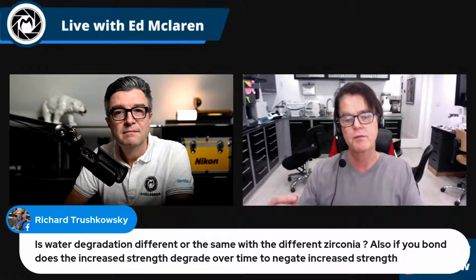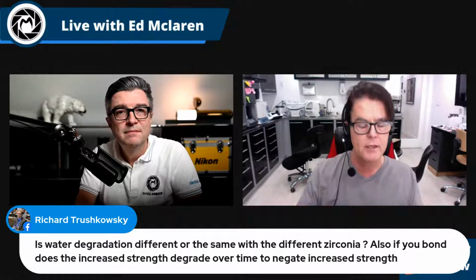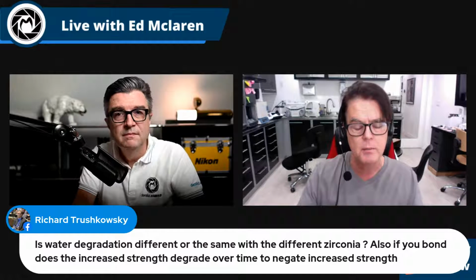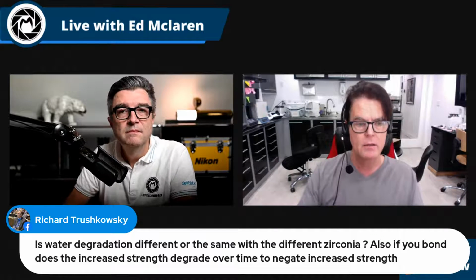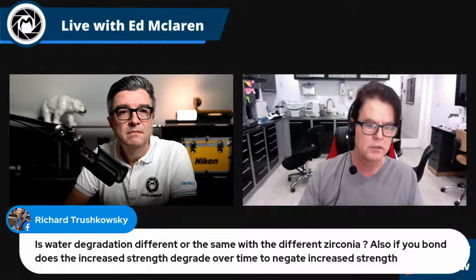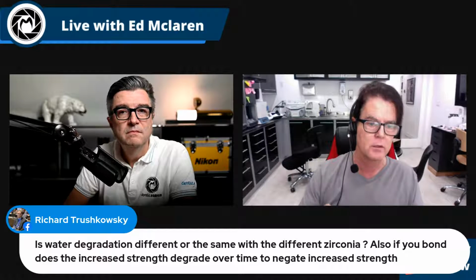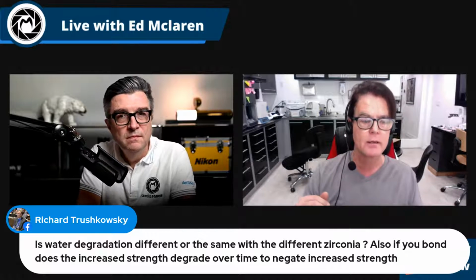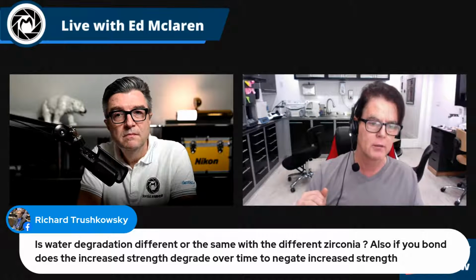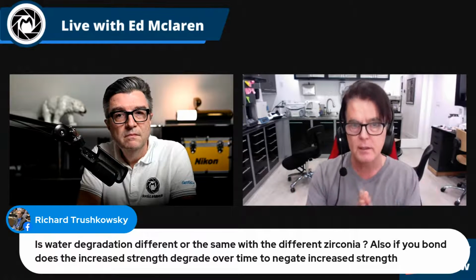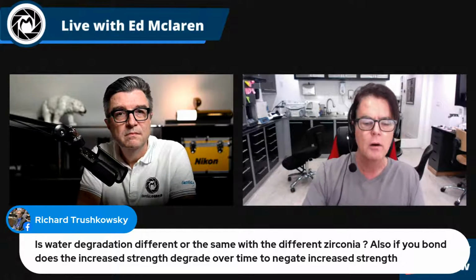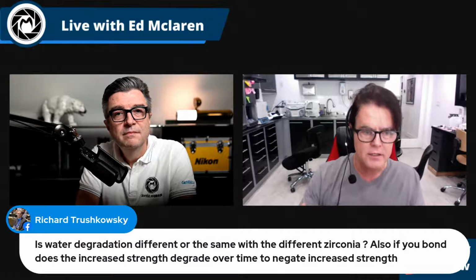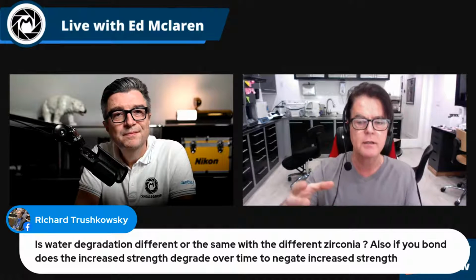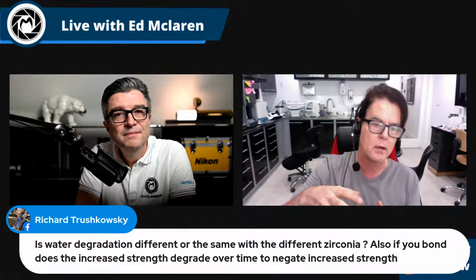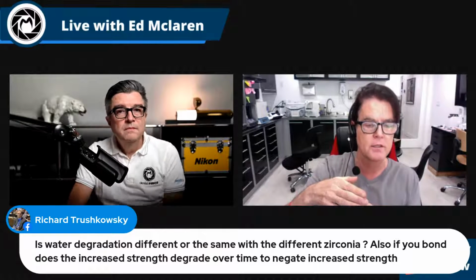All right, so let's fast forward to dentistry. When the FDA, and I don't know about the governing bodies in Europe, made the companies put in alumina, somewhere between a quarter to 0.5% of alumina. If you add that, you don't get hardly any low temperature degradation, at least with normal firing, at least now we know with normal firing. All right, so now here's the interesting thing. Now remember, if we seal a surface of a crown to the tooth, we're not having a problem on the inside unless there's leakage.